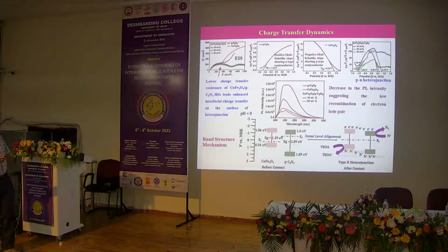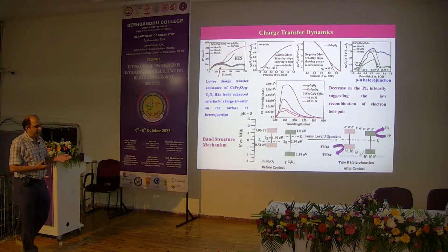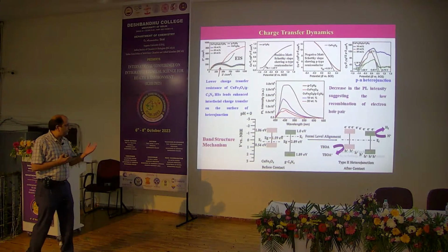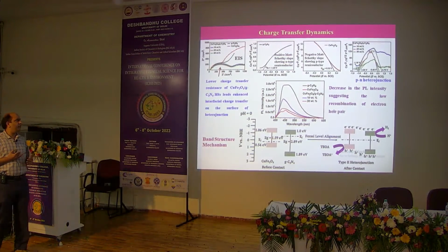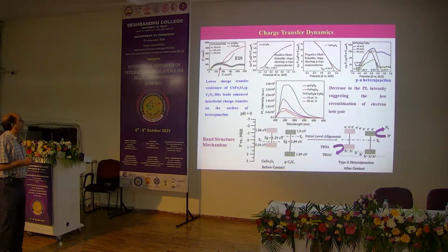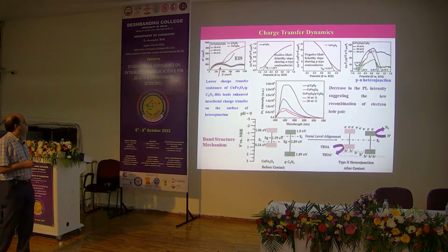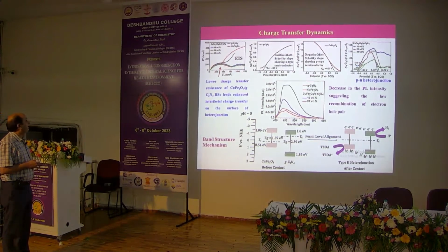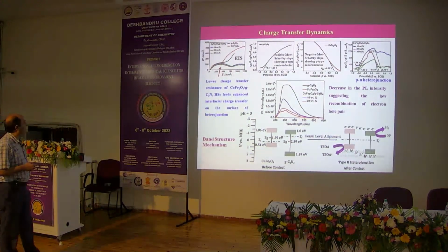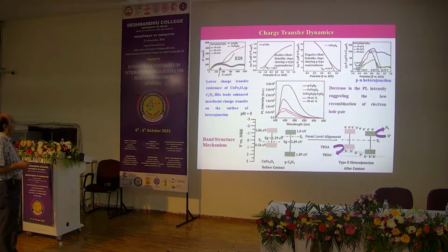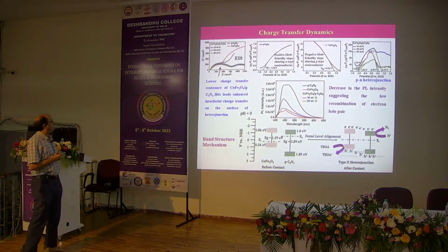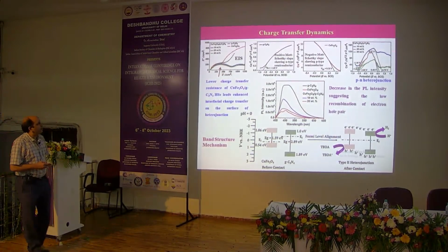These are the charge transfer dynamics which we studied to see the electron-hole pair structure, and the band structure mechanism we have also explained over here. This is the impedance spectroscopy. The low semicircular ring refers to the low charge transfer resistance, which leads to enhanced interfacial charge transfer. And these are the Mott-Schottky plots.